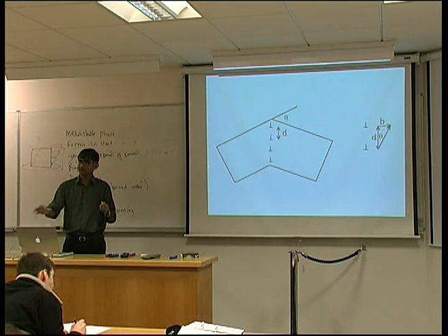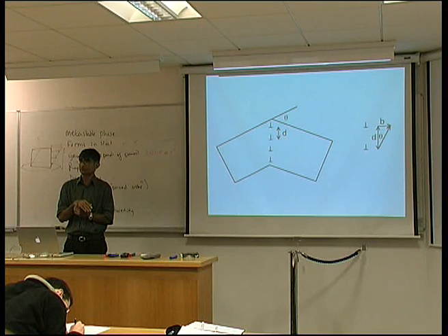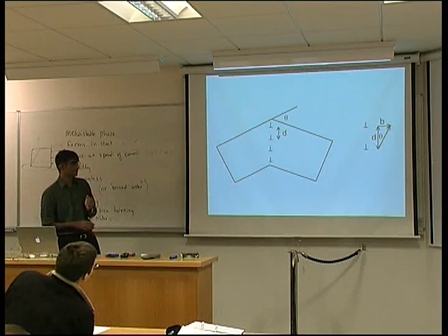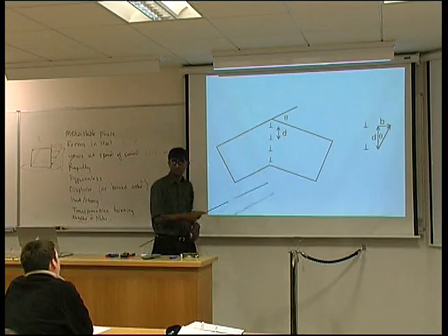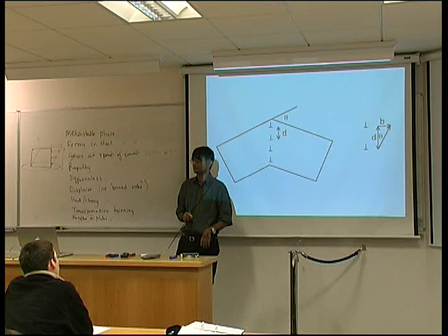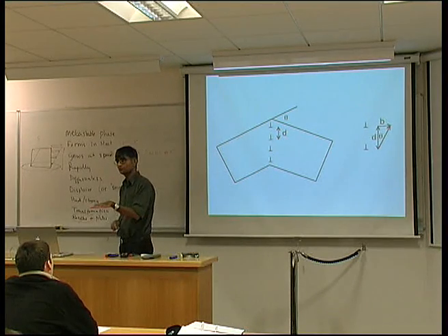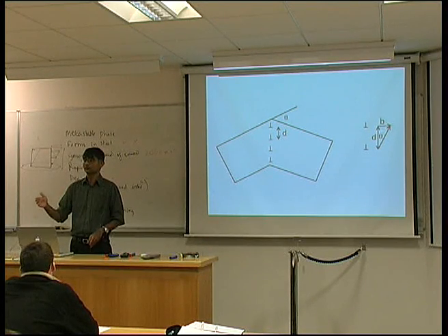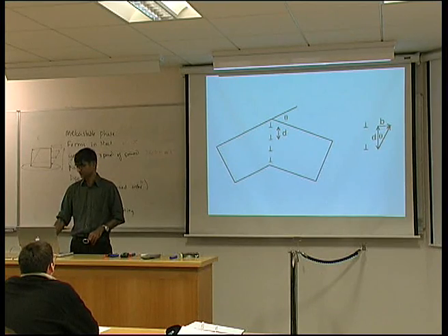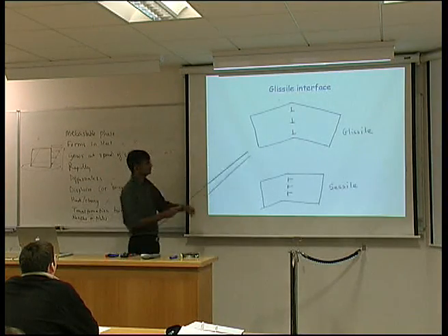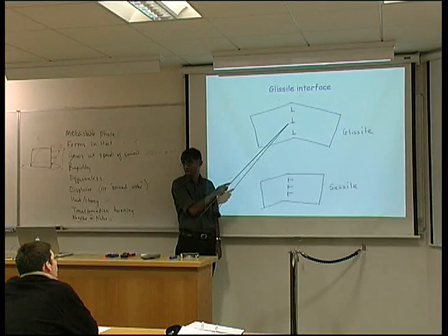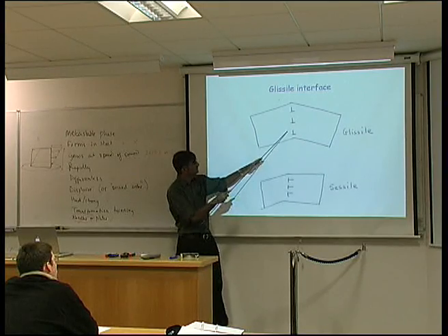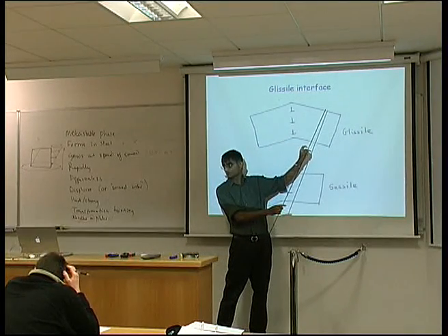Now, remember that martensitic transformation can happen extremely rapidly. It can happen at extremely low temperatures, which means that we cannot arbitrarily put any kind of dislocation there for martensite. It has to be a dislocation which can move without diffusion. So the translation of the interface cannot require diffusion. And therefore the Burgers vector of your dislocation must lie outside of the plane of the interface, because then the whole array can translate without diffusion.